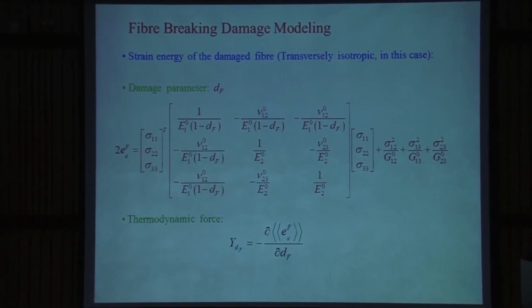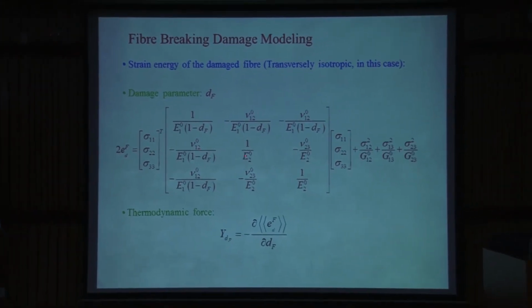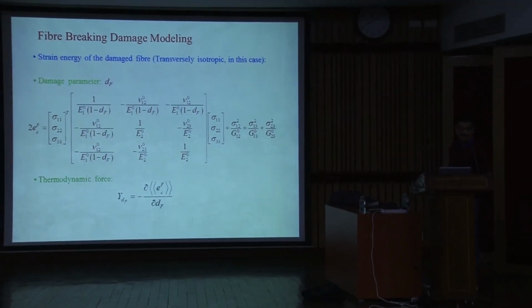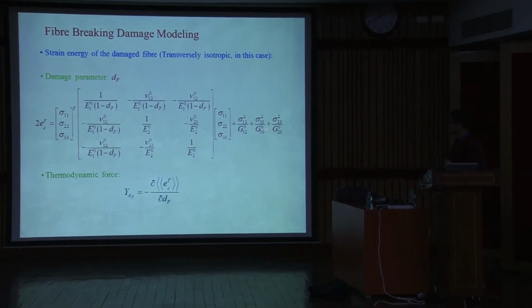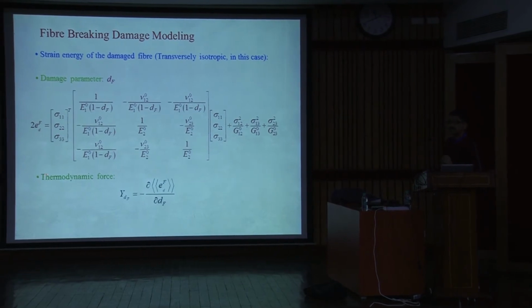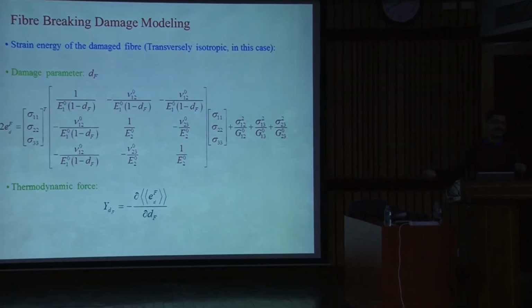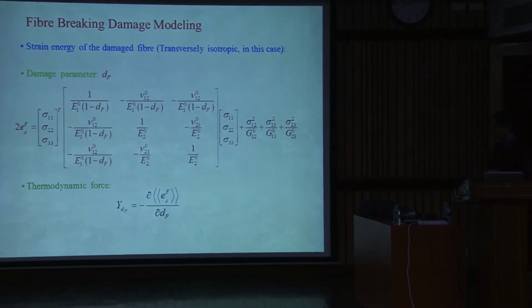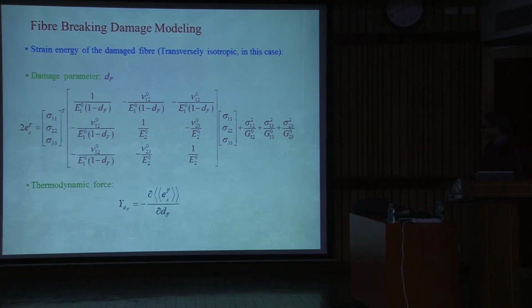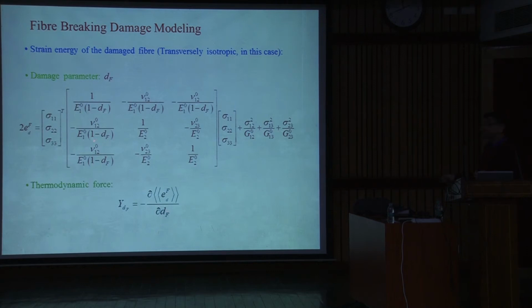Okay. As we said, this material is orthotropic. So you will have E1, E2 and E3. E2 and E3 are the same because this material is transversely isotropic. That means the behavior in the 2 and 3 directions is the same, but in the 1 direction it is different. Okay. So this is the strain energy of the damaged fiber, given like this. It is affecting only the Young's modulus in the length direction of the fiber. It is not affecting any other. Okay. And if this is your strain energy, then you can define the thermodynamic force in this way. Okay. Where dF is the damage indicator for fiber failure.